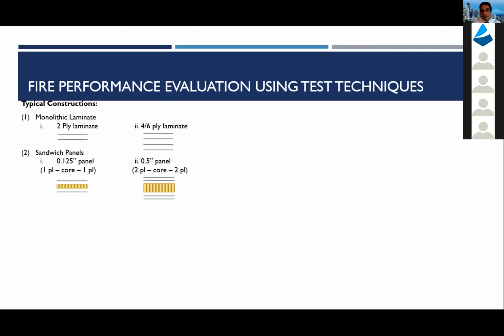whereas in sandwich panel constructions, 1-ply core with a 1/8 inch panel, and 2-ply core with a half-inch panel are used for the test. Then, in the test, first it goes through the flammability test, where the sample dimension is 12-inch by 3-inch for the coupon, and the orientation of the sample is such that the 12-inch side is held vertically.